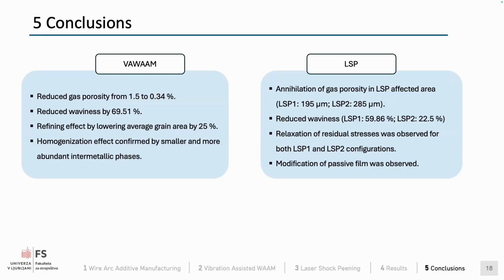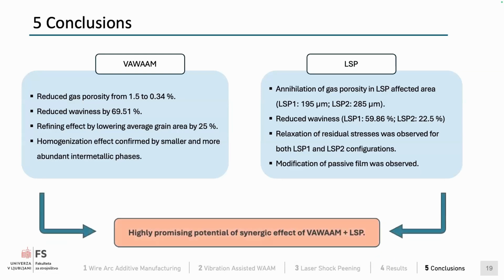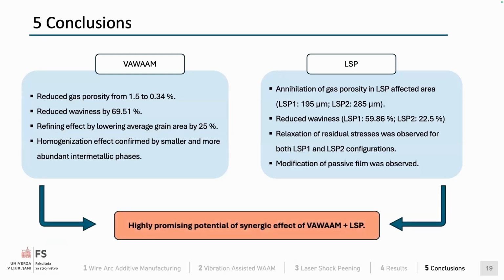Relaxation of residual stresses was observed for both of the configurations, and the modification of the passive film was observed, which will be a very important aspect in the future electrochemical corrosion testing. So this is our conclusion.